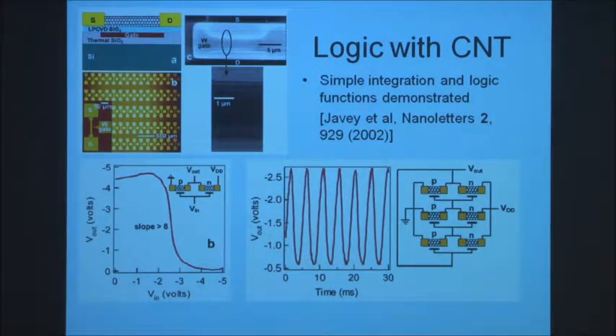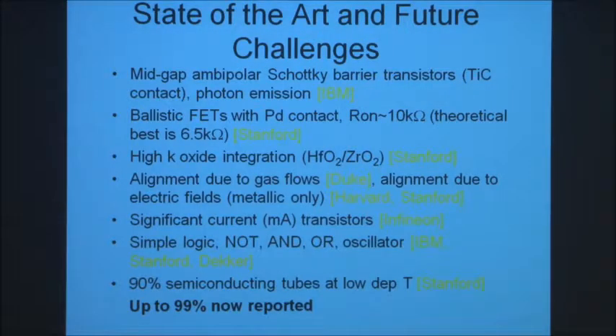You can do that, and many other people have done it as well. This is some of what Javey did a few years ago, which is looking at shift registers and inverters. And over the past N years, people have done more and more of this. So you can now do ambipolar devices, ballistic field effect transistors. You can use high K. You get high current transistors by having lots of CNTs in parallel. Lots of simple logic has been done. And nowadays, people get up to, by controlling the growth better, maybe up to 90 or even 99% of the tubes will be semiconducting, which makes it a lot easier to make transistors.